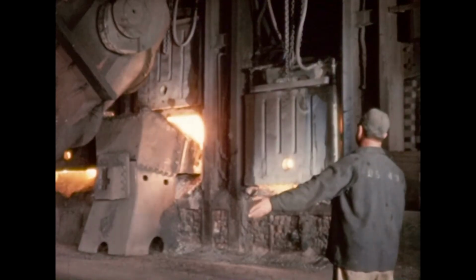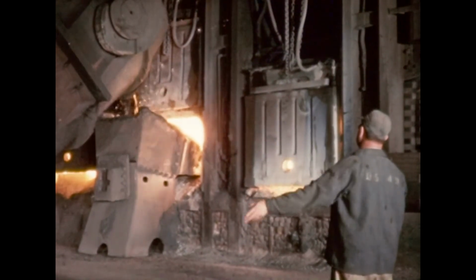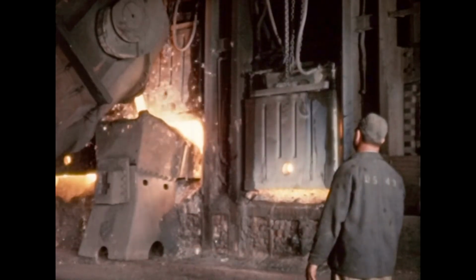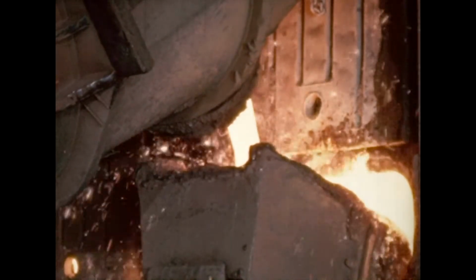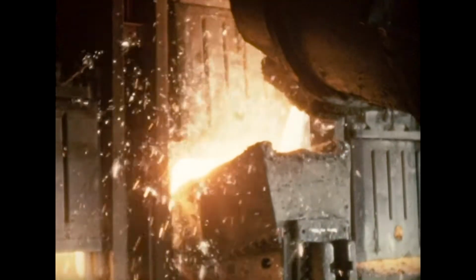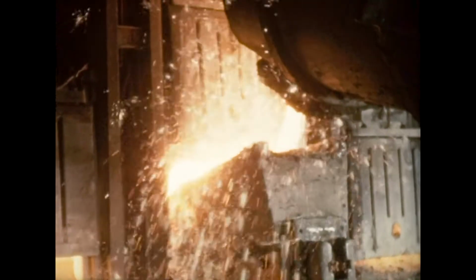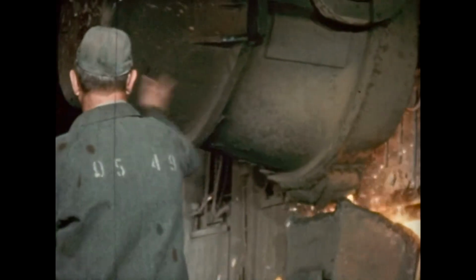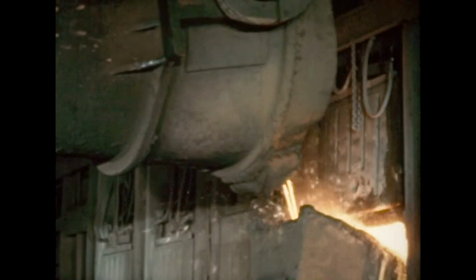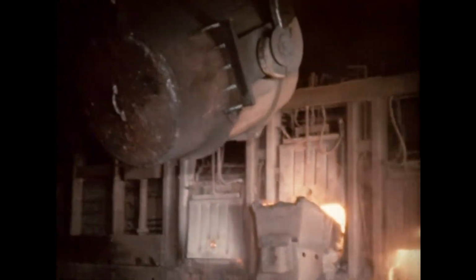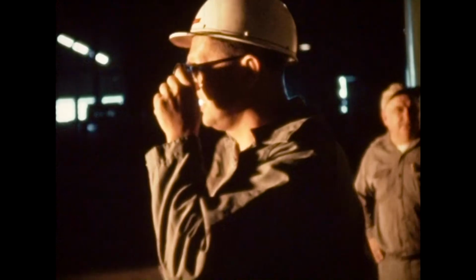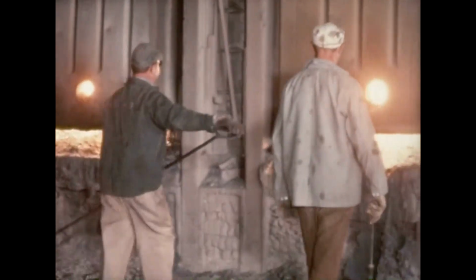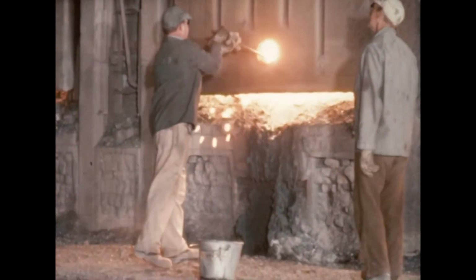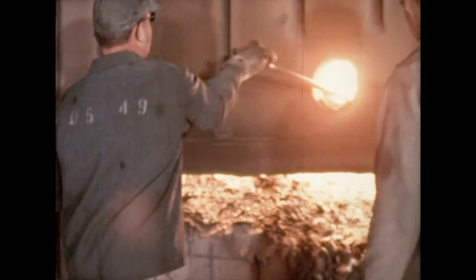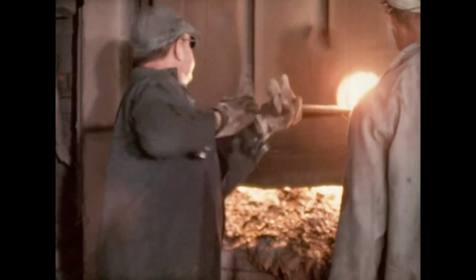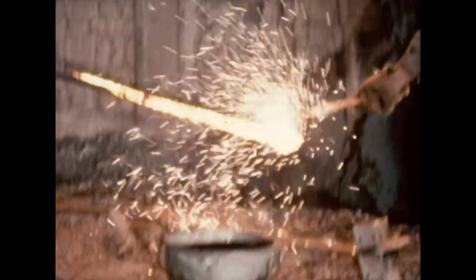In the open hearth furnaces, the iron, mixed with selected steel scrap and other ingredients, is converted into steel. Of all the steps in steel making, this is the most critical. Steel has thousands of uses and hundreds of different specifications. In a heat of 312 tons, the melter must be concerned with alloys measured in pounds and calculated in terms of thousandths of 1%. The melter must know the exact percentages of sulfur, carbon, silicon, and phosphorus present in the heat. To determine this, samples are taken at the start of the heat and at intervals during the melting.